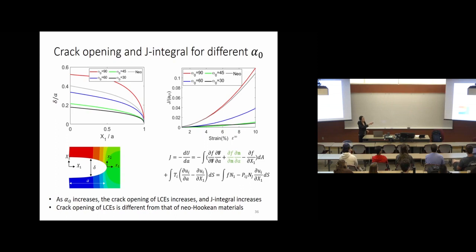For initial angle alpha equals 90 degrees, which means parallel to the stretching direction, the crack opening is much larger compared to other cases. That's because your director does not rotate a lot. Therefore, the material itself is stiff, and you have to open the crack a little bit more. But in other cases, the directors themselves can rotate, giving rise to the displacement. Therefore, you don't need to open the crack too much.